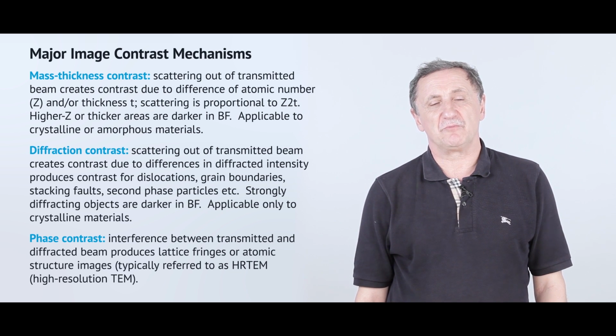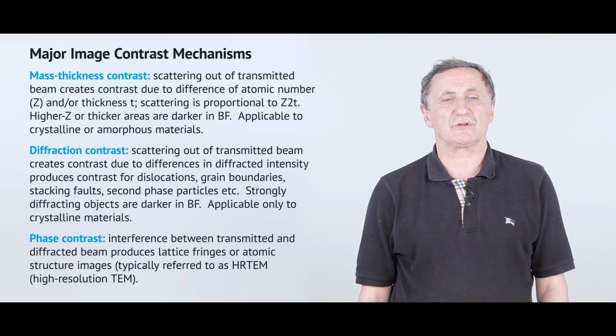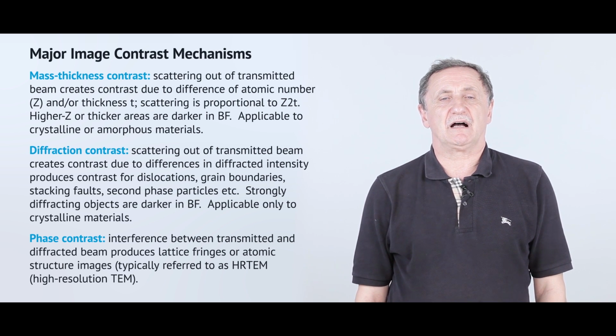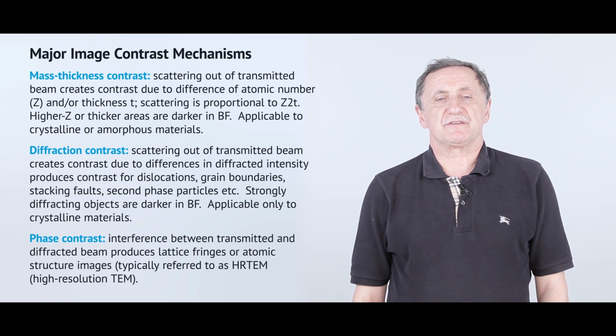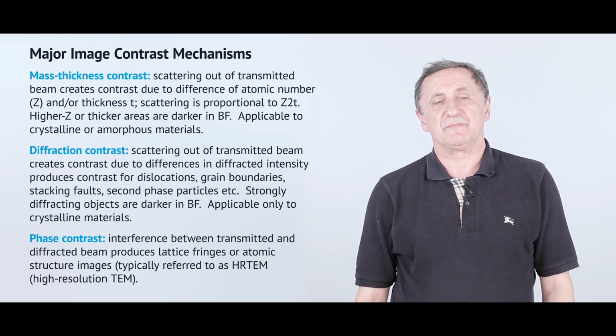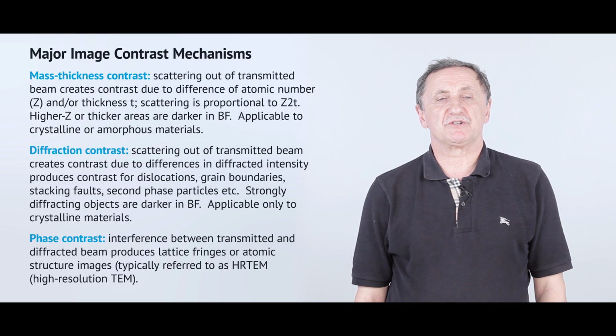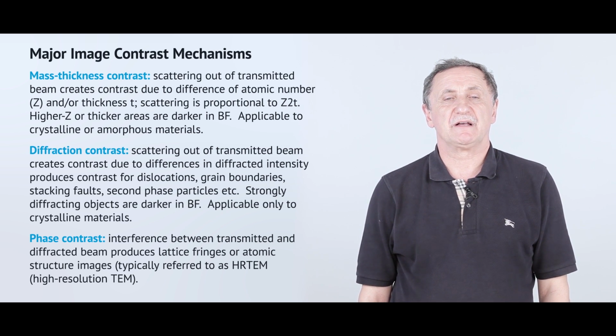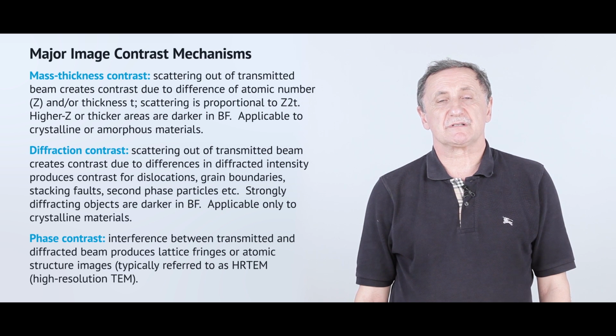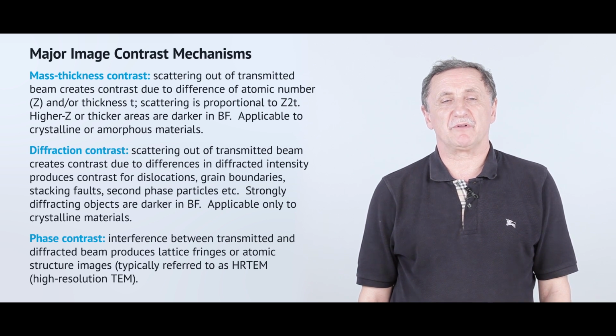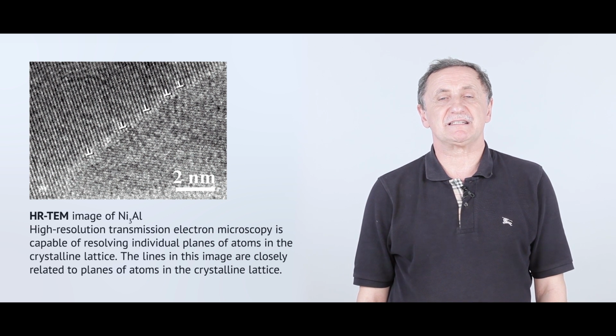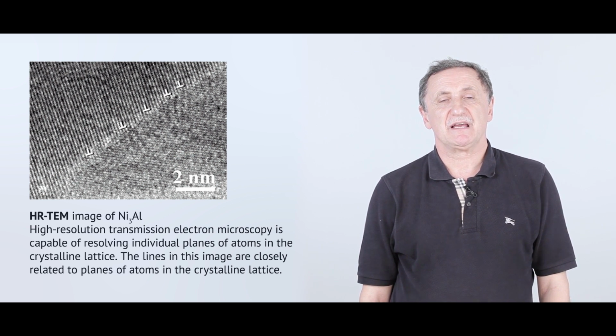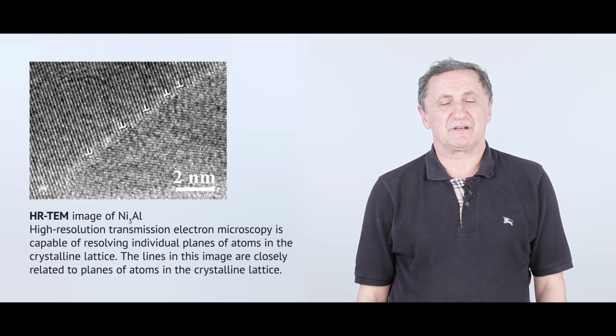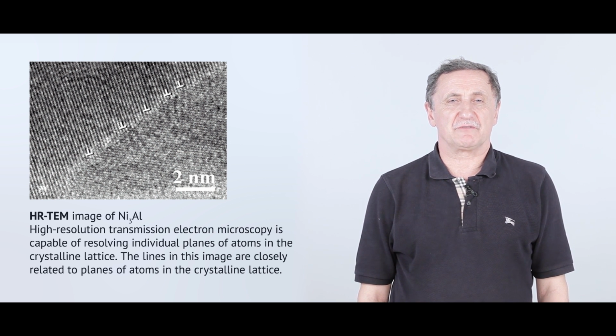And finally, as for me, the most complicated type of mechanism is so-called phase contrast. This is the interference between the transmitted and diffracted beam, as I showed you in the case of the lattice imaging, which provides you some information about the atomic arrangement of your sample. This is the so-called high resolution TEM images. And when all these 3 mechanisms work together, sometimes it's very difficult indeed to provide the right interpretation of the obtained results.